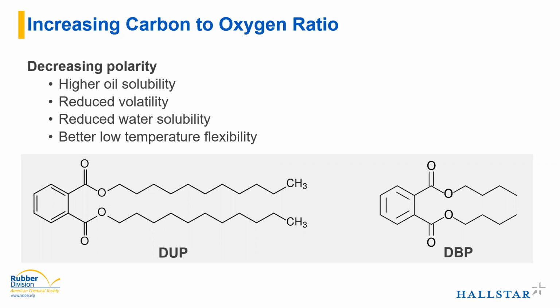Oils are very nonpolar, so as you decrease polarity of your ester, you'll see more solubility in oil. You'll also see a reduced volatility because the ester will always be present. As we decrease polarity, that means we're making the molecule larger, so it's going to be less volatile than a very small molecule like that on the right.